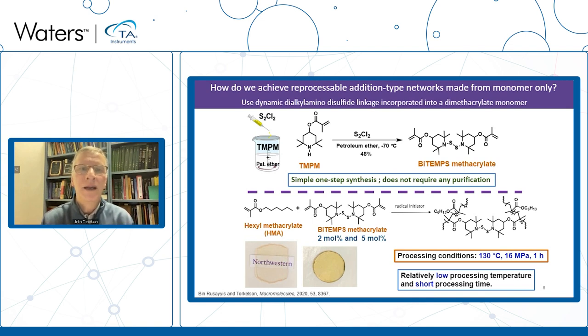And we can basically put this crosslinker between two carbon-carbon double bonds. This BiTEMPS methacrylate molecule will effectively work as our crosslinker if we are reacting this with monomer that has a single carbon-carbon double bond. We do free radical polymerization in these cases and then end up making a network in these circumstances.